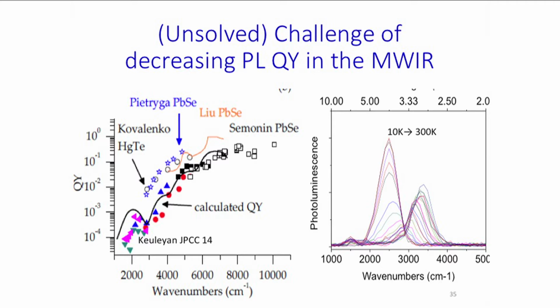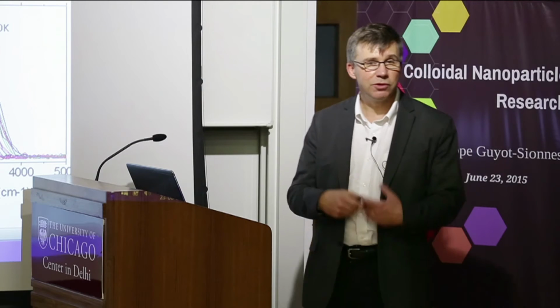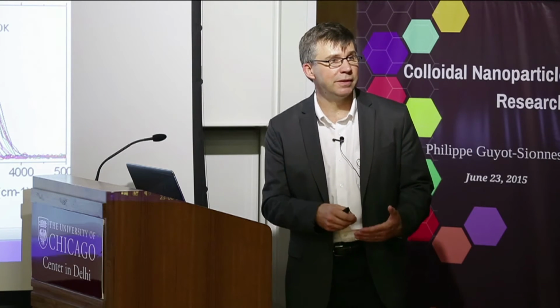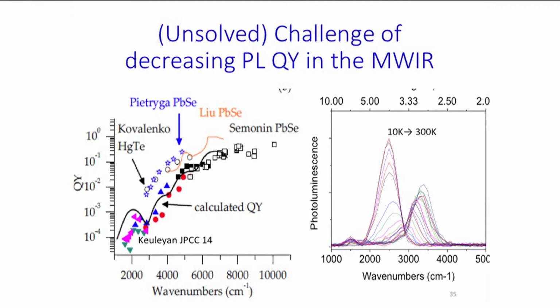A part of it is the molecular ligands. And this is shown here. This is one sample of mercury telluride quantum dots, and what we do is change the temperature. And as we change the temperature, the wavelength shifts. That's because of the band structure changing a little bit. And so what we see is, going from low temperature to room temperature, the fluorescence decreases initially. So traditionally you'd say, oh, there are traps or something is happening. And then it increases again.